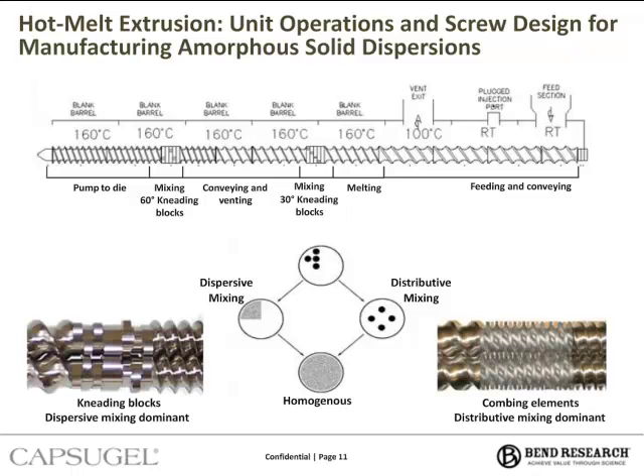And typically, HME has about 5 unit operations. The first one is feeding, and this takes place in the first part of the screw. Now the polymer and API can be introduced independently or as a blend. And this is done volumetrically or gravimetrically, and the powder enters via feed throat, as seen in the schematic. The feed barrel is actively cooled to prevent low melting point material from sticking.